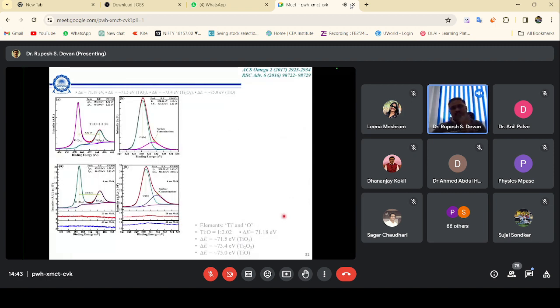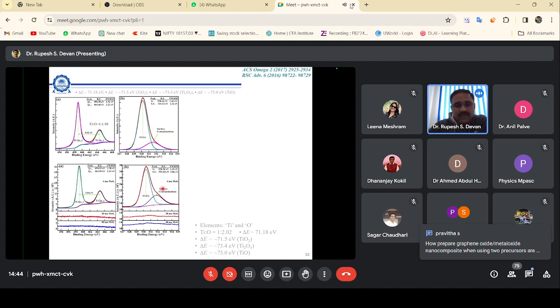After that, the question here was, when you are putting MoS2 on the TiO2, MoS2 itself does not require oxygen, because when it comes in contact with oxygen, rather than forming MoS2, at the interface it may form Mo oxide, which we don't want. So we tried to understand what happened at the interface. TEM was not giving us the information because these two phases were prepared independently in two different systems. So when you scratch out the sample and check with TEM, both are independent. So finding out the interface was a difficult task.